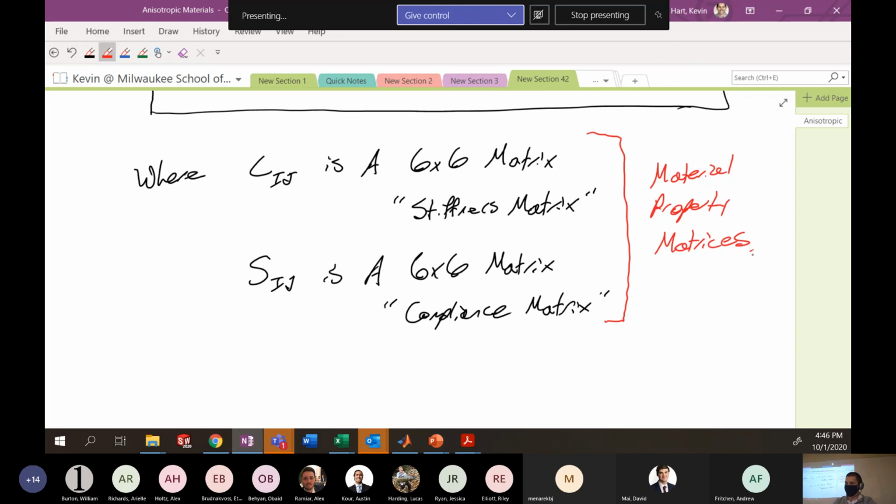So this is the first stepping stone to getting you to think about how a general anisotropic material might have 36 independent material constants. It's a lot. Isotropic materials are represented with 2, E and nu. General anisotropic material represented with 36. Yikes. The lectures to come will focus on populating this matrix and how we deal with the symmetry conditions we might see. That's it for today.